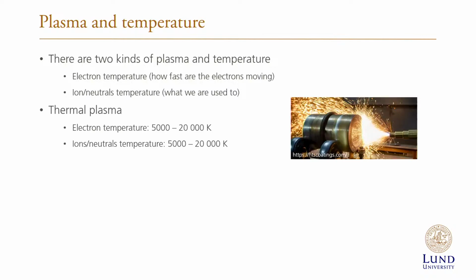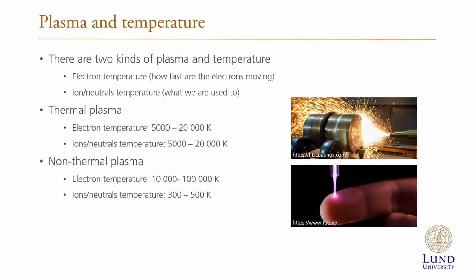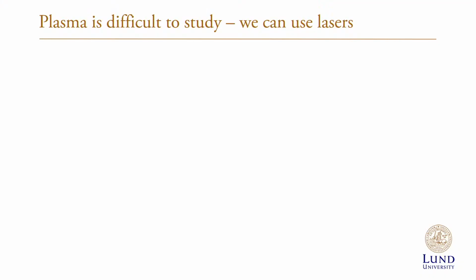So in thermal plasma, the electron temperature and the ion temperature are the same. It ranges from several thousands to tens of thousands of degrees. So it's really, really warm. And then you have non-thermal plasma, where the electron temperature is really high, but your gas temperature is low. So that's what you can put your finger in. It doesn't really hurt. And then, of course, there are all these intermediate things. So what if you can use non-thermal plasma, where you put less energy into it, and still have a very reactive environment? So how do we study this?